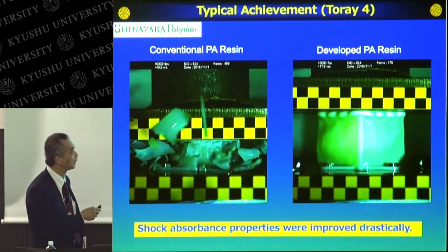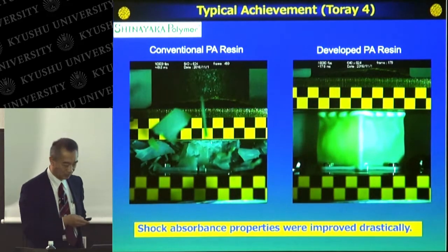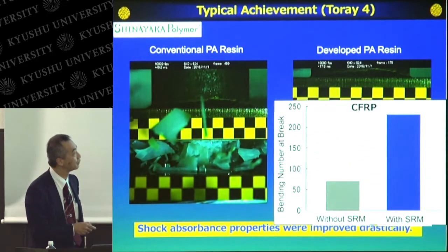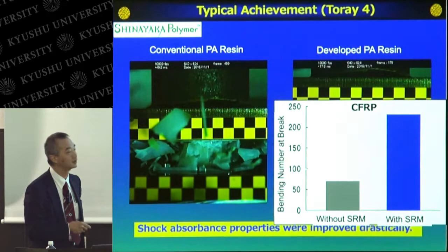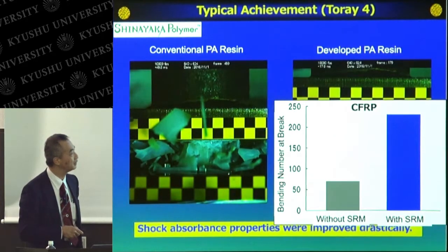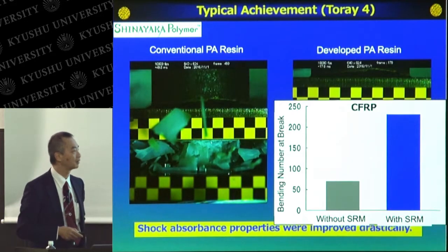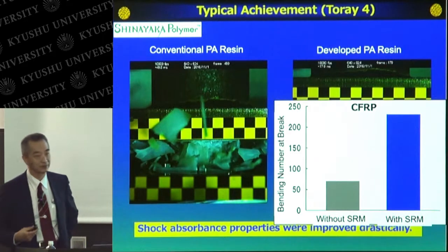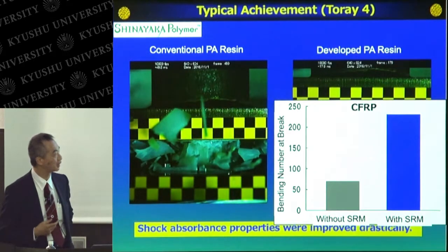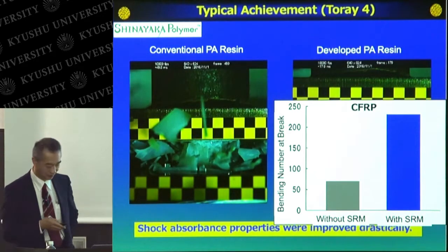So these are results for the polyamide resin, but it can also be used for CFRP epoxy resins. In this case, the bending number at break is increased about 3 times by using sliding materials in the carbon fiber composite with epoxy resins. Okay.